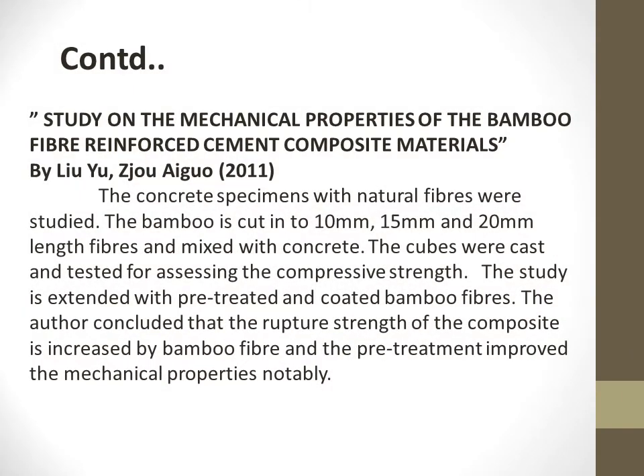This is the journal by Liu and Ziog on the title Study on the Mechanical Properties of the Bamboo Fiber Reinforced Cement Composite Materials. They cut the bamboo into 10 mm, 15 mm and 20 mm length fibers and mixed it with concrete. He casted the cubes and put them to compressive strength test. They pre-treated it, and then they concluded that there is an increase in the rupture strength because of the pre-treatment done to the bamboo.